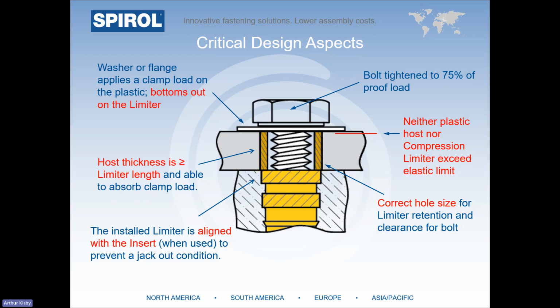There are always ways of achieving the critical metal on metal on metal contact to optimize your joint, while also maintaining some plastic compression. In some instances, though, we'd want to partner with you in order to provide application-specific recommendations. Just like with the plastic, we also need to make sure that the bolt does not exceed the elastic limit by assigning a clamp load of about 75% of the proof load. If an insert's used, like in the example shown, the limiter should be well aligned to prevent a jackout condition. And lastly, the hole size is critical to ensure that the compression limiter can retain its position within the assembly prior to the bolt being assembled.